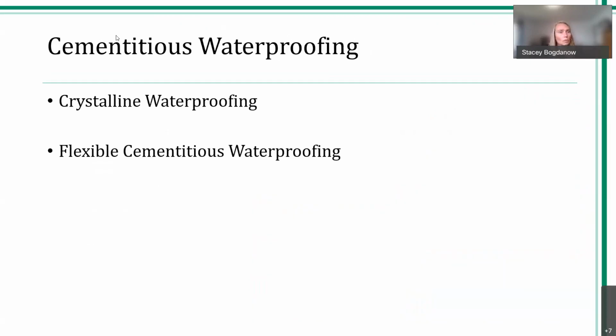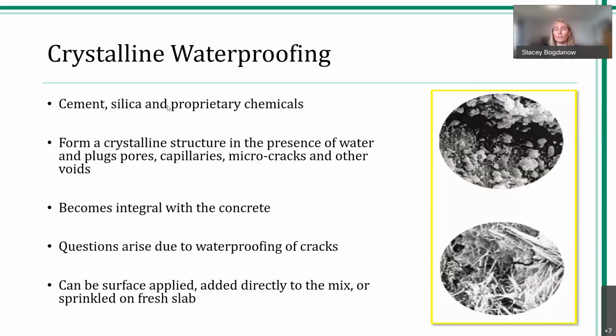Cementitious waterproofing, before I was talking about crystalline and flexible. Crystalline, one of the things is that it's all about water, the way that it penetrates into the concrete. It has to have a surface saturated, at least 24 hours saturated with water, so that when you're placing the slurry onto the concrete, the water is able to bring the crystalline into the concrete and waterproof it. Also, you need to wet cure it for 3 days afterwards, again, to get the water, the crystal into the concrete.